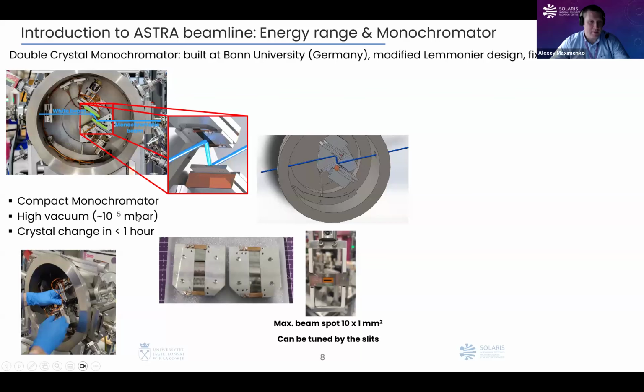And what does it mean? It means that we can easily open our monochromator and change the crystals which we have in it. Here you can see the crystals, these gray silicon crystals installed in aluminium holders. And in order to change the silicon crystals, let's say to germanium 220 crystals, we just open our monochromator, put them in, close the monochromator, and we can operate within 1 hour.